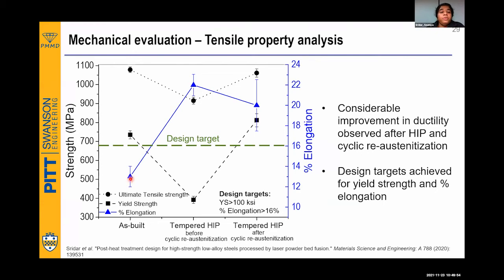But the improvement in elongation is considerable. Here it was only 13% elongation. However, we are almost hitting 20%. Of course, the tempered HIP before cyclic reaustenization has higher elongation because it has more of that soft phase, which is the bainite. However, its yield strength is very low. So from this design, we have achieved the design target. We have reached close to 20%.